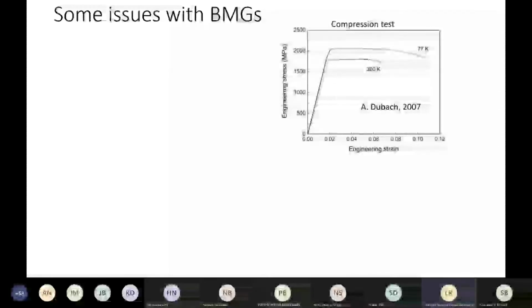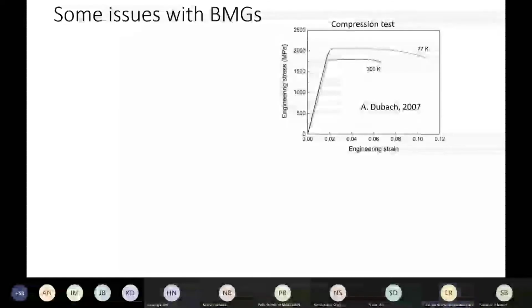If you look at a metallic glass which is compressed, it shows a lot of plasticity. Essentially, here there's a curve. You see the engineering stress versus engineering strain curve, and you're doing a uniaxial compression test. What you see is that a metallic glass can undergo a strain of about 0.8% when you do it at 300 Kelvin. But when you do the same test at 77 Kelvin, it shows more plasticity. And when you see the material after it has been compressed, you will see that it contains several of these slip line like features.